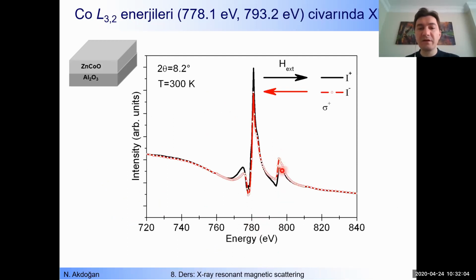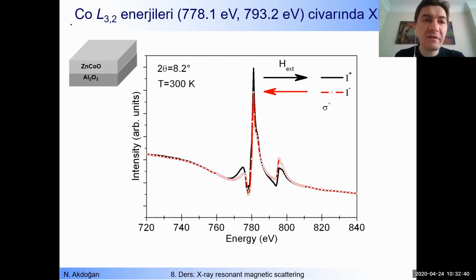So here we have this one, 793.2, and here within that range we have this one. So if you start earlier and if you finish later on, then you can see that range of the cobalt L2 and L3. Let me draw the measurement geometry again. This is the incident X-ray beam coming with theta angle. This is 4.1 degrees and goes to detector.